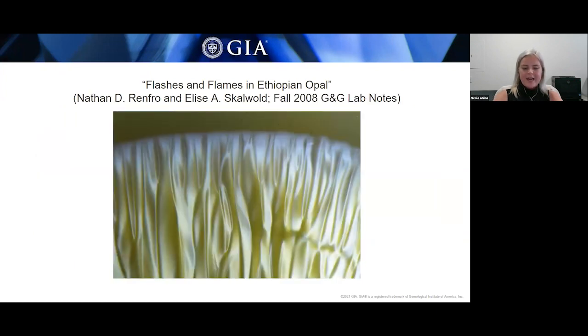If we take a closer look, here in this photomicrograph, you can see that structure. They're using oblique fiber optic illumination to make that sheen visible, and the structure becomes more defined. The cause of this structure is unknown, and Raman spectroscopy did not pick up any other mineral present. So it is thought that a pre-existing fibrous mineral was replaced by opal. But even without knowing that, this stone still joins a small group of chatoyant precious opals that we get to see every once in a while.